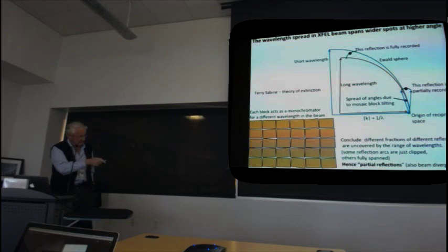Now, what we need to think about is what the reciprocal lattice looks like for a mosaic crystal. Each of these blocks makes its own reciprocal lattice, but the blocks are tilted. So if you imagine a reciprocal lattice vector starting from the origin here and tilted around in all possible angles, or think of the Euler angles, you'll see that it traces out a kind of hemispherical cap. This curved line in green here is a spherical cap at the end of the reciprocal lattice vector. I've got to do that on every reciprocal lattice vector, so there'll be one up here.